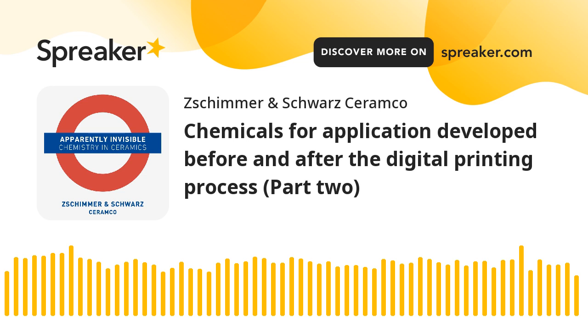What can we do to avoid this problem? We can say that we could take different actions, but three for sure are the most effective. First, when possible, of course, it is recommended to increase the temperature within the dryer to promote a complete or almost complete evaporation of the water content before the following digital printing process.